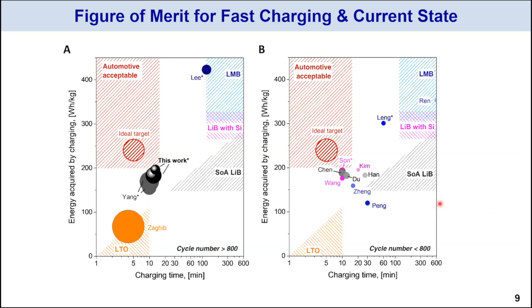Now in the emerging chemistry or system area, by and large, you see all those tiny, teeny bubbles. Those are needs, meaning there's not sufficient life and we need improvement. In particular, there are a few pink points here and they all have bubbles that are too small, meaning that the cycle life is too short, and that is consistent with the biggest issue facing silicon anode batteries. Basically, they are lacking sufficient calendar life. Therefore, I think dealing with stability and durability of silicon batteries is still the biggest challenge before we consider fast charging. And for the lithium metal batteries, you also see a few data points spreading around, and probably